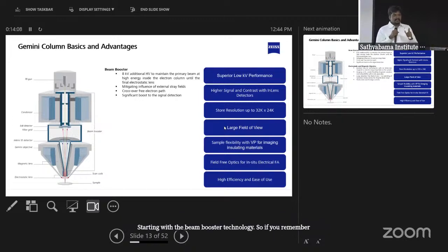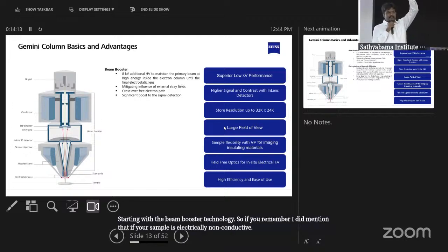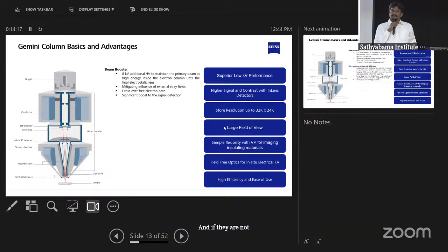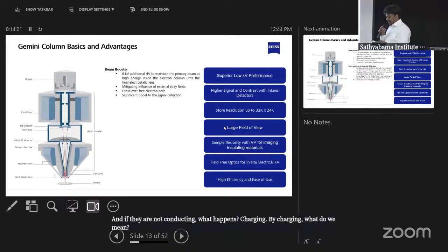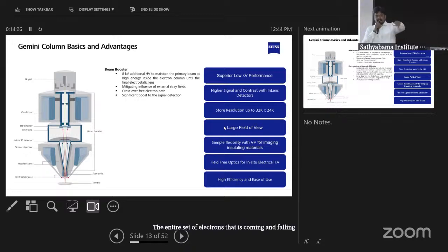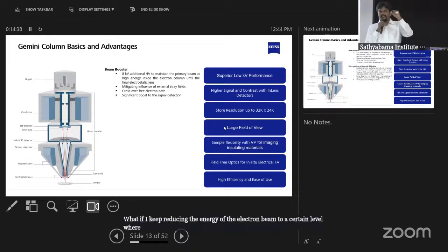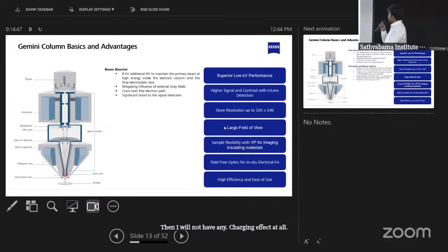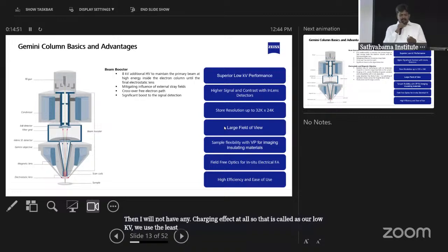If you remember, I did mention that if your sample is electrically non-conductive, and imagine the current coming and falling on your sample, and they are not conducting, what happens? Charging. By charging, what do we mean? The entire set of electrons that is coming and falling on the sample surface starts accumulating on the sample surface. So that's why you're not able to see anything. Now, what if I keep reducing the energy of the electron beam to a certain level where the minimum energy required for interacting with the sample is good enough? If I do that, then I will not have any charging effect at all. That is called low kV. We use the least energy of electron beam that interacts with the sample. So without any challenge, you can start characterizing non-conducting samples, or even insulating materials as well. I have a few data to share, and it could be life science samples as well. No challenge. So that is something unique for Zeiss, this particular architecture.